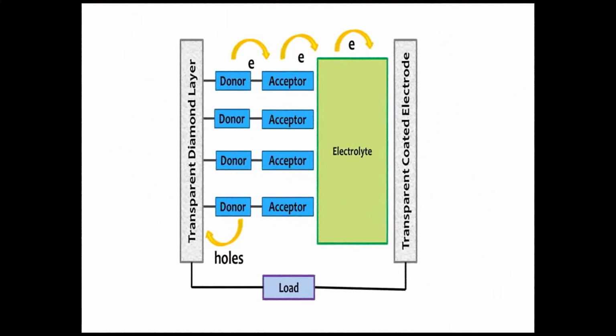the diamond electrically conductive. The advantage of having these charges in there is that by then fixating a dye on the surface, which captures the solar light, these charges that are created by capturing the light can then be transferred into the diamond substrate and onto the continuous layers which are forming the complete device.